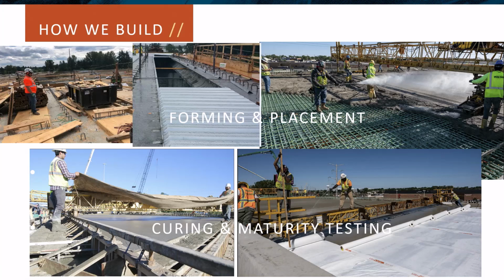Typically, if you're using corrugated metal pans, those corrugations actually restrain the concrete and cause some of the cracking that we see from time to time. During placement, are we adding too much water? There's all sorts of things that can happen with trucks and delivery, and we're just kind of stuck with what we get at that time. And then curing and maturity. We're doing cylinders today, we're adding burlap, but there's a lot of new technologies and things that we can do today to help improve that process.